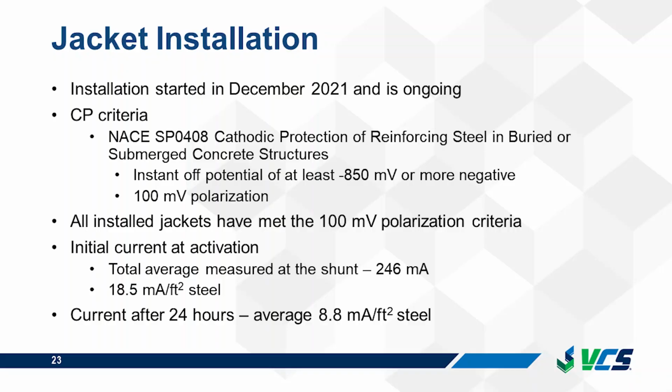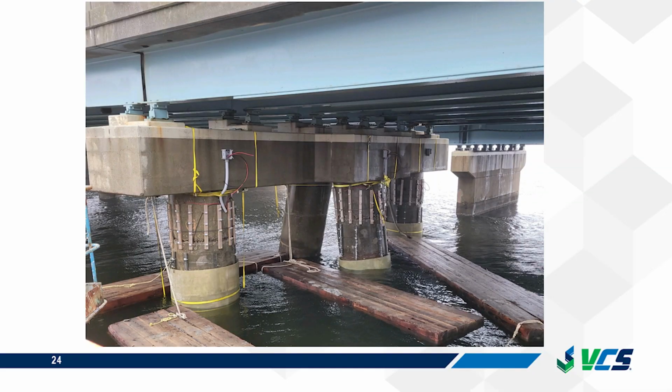So initial current was 18.5 milliamps per square foot, and then after 24 hours, the average was 8.8 milliamps per square foot.